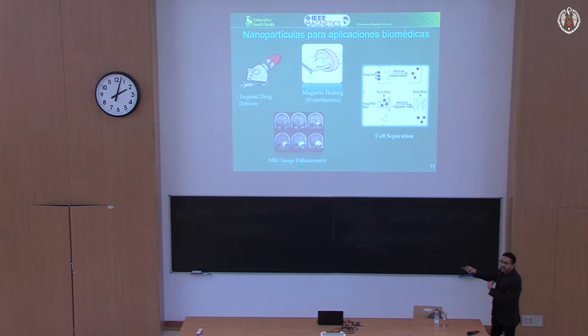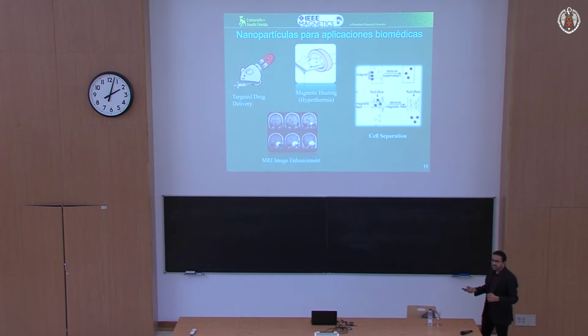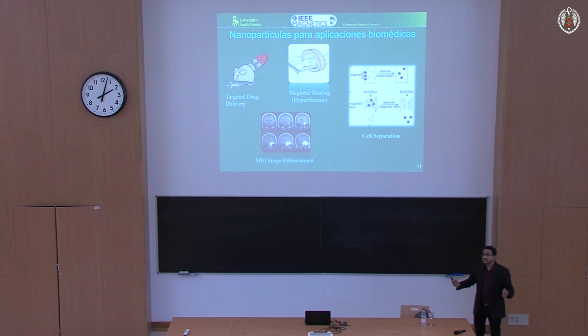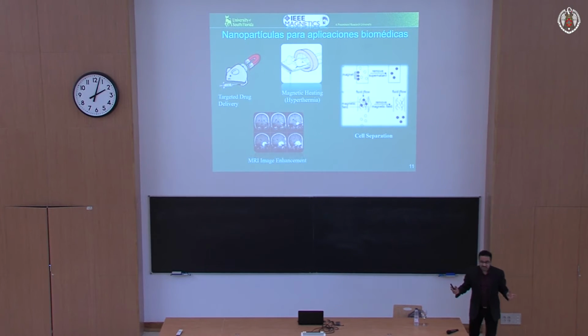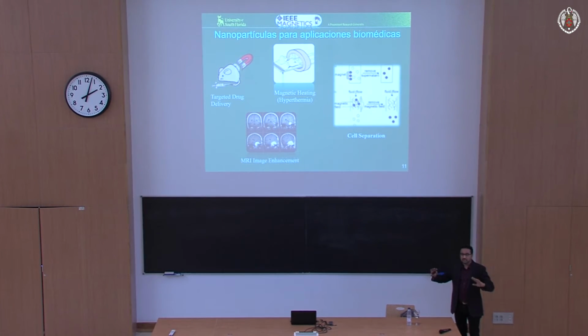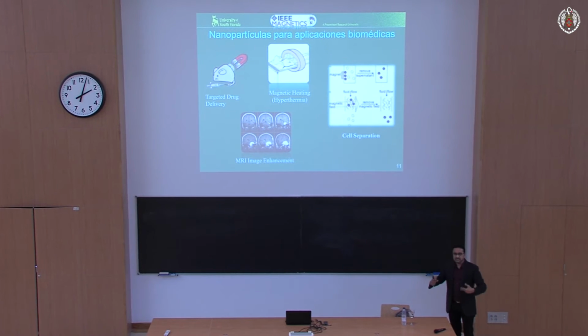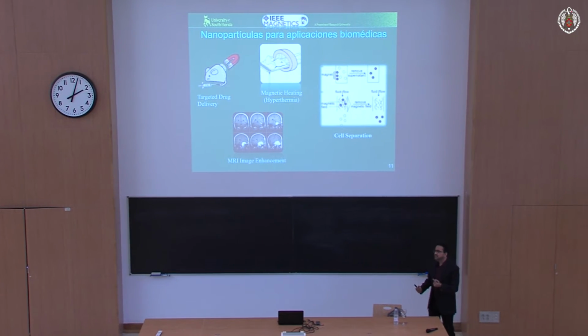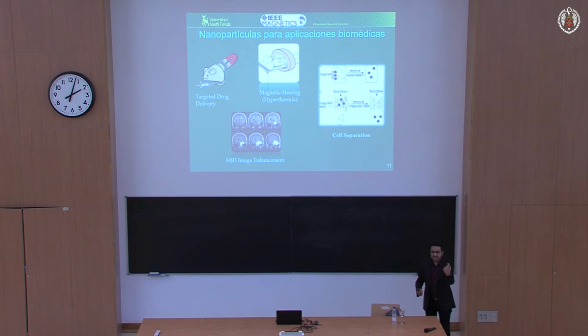Here's another area, and we have some work in this area too in my group. We can actually use magnetic nanoparticles for enhancing the quality of MRI images. MRI, as you know, is a well-established technique available in most hospitals for brain scans, tissue scans. It works on the principle of NMR, nuclear magnetic resonance. The idea here is to excite the water protons and make them precess by a high frequency radiation, and then you remove this field, so there is a dephasing or a relaxation. There are several relaxation times here, T1, T2. We won't go deeper into this, but from the relaxation time, T2, you can make images like this. So that's the conventional MRI.